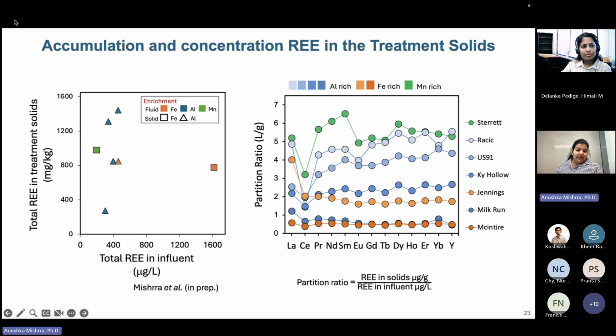The other thing, like I said, is how this enrichment happens - we can look at a partition ratio. This is basically all the REs going from solids to influent. So you can see for the manganese enriched fluids, we have the highest partitioning ratio. This is because in the AMD fluid, there were low concentrations of RE, versus in the solid, we had very high amounts of REs comparatively. So that's why the partition ratio is high for it.